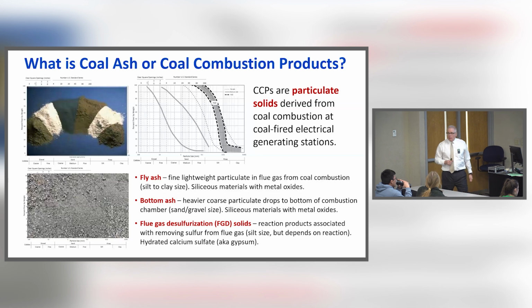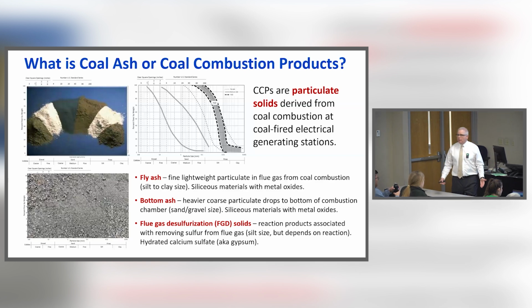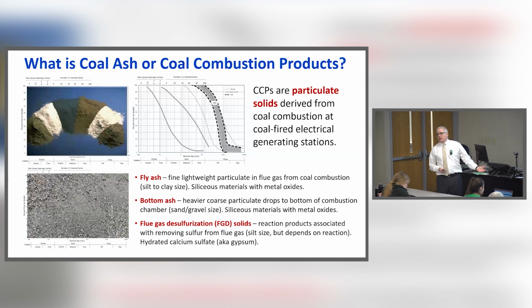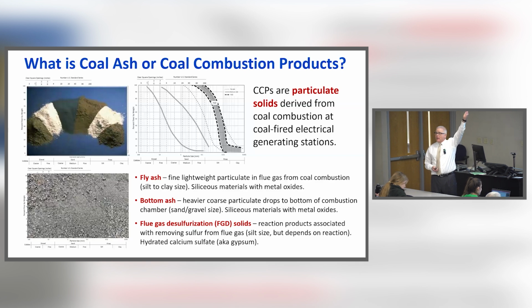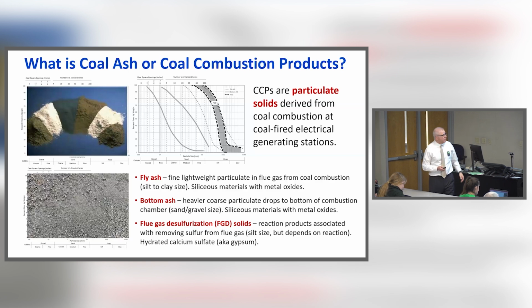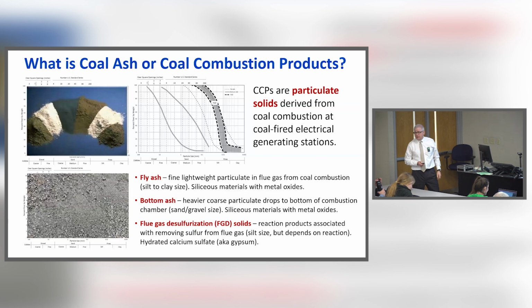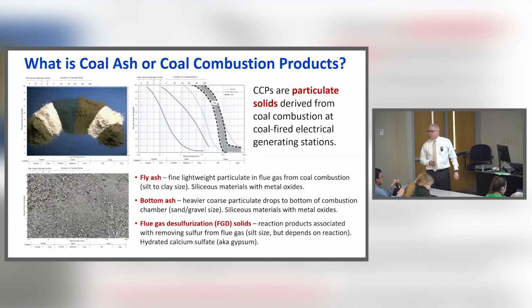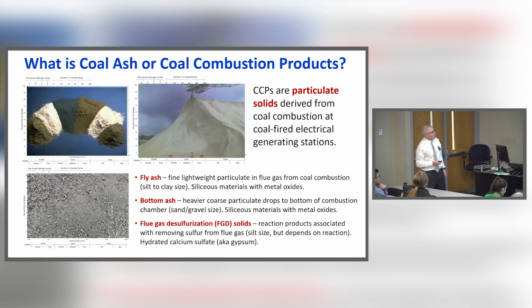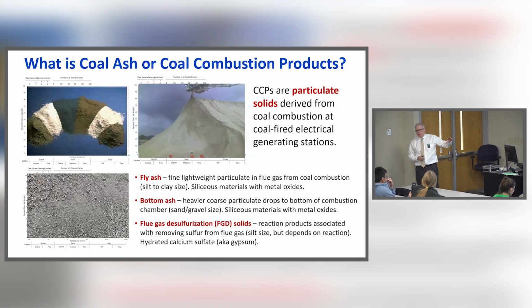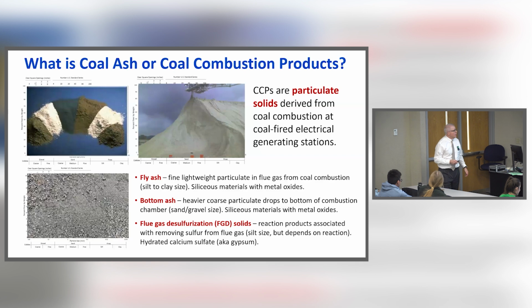So we burn the coal, we have sulfur in the coal, we'll burn that coal, and that releases sulfur into the flue gas. And if we don't capture that, we generate acid rain. So we'll capture that sulfur as well. That's the so-called flue gas desulfurization residual, or FGD. We have to have a good acronym for everything. That's also fine textured sludge type material. Just a photograph of that as well. That tends to be a hydrated calcium sulfate.